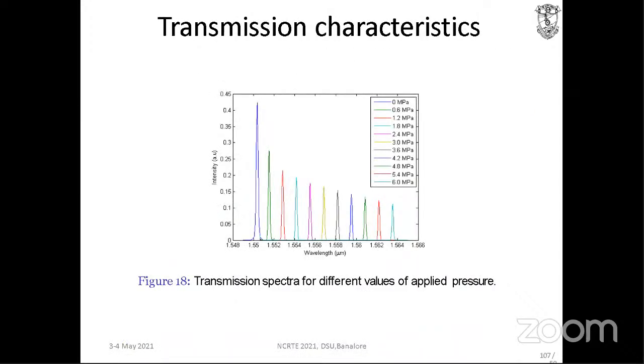Figure 18. You can see the first one is 0 megapascal, coming at around 1.56 micrometer wavelength. On the right side you can see the application of different pressures. There will be a change in refractive index, and because of the change in refractive index you are going to get a change in wavelength. For example, the last one is for 6 megapascal, you get 1.564 micrometer, and previous to that is 5.4 megapascal. Depending upon the applied pressure, you get different refractive index values and therefore different wavelengths.